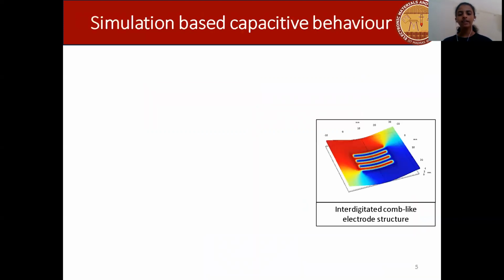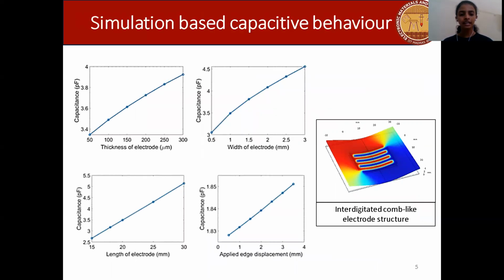In the first case, where I considered an interdigitated comb-like capacitor, I have observed an increase in capacitance with increasing electrode dimensions. That is, all the three: thickness, width, and length of electrodes. This is very evident as we know that with increase in the amount of conducting material in the device, we can observe an increase in capacitance. And here we can see that the capacitance in plane condition for these devices is in the range of 3 to 4 picofarad.